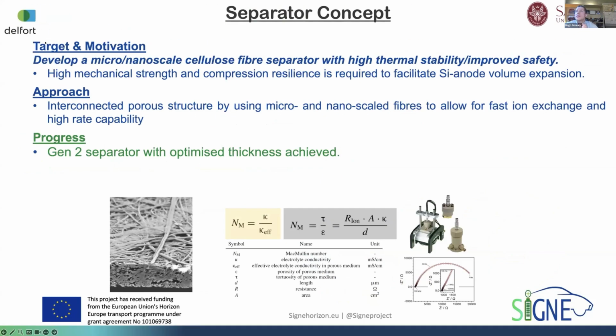On the separator side of things, so these are cellulose-derived fiber separators being developed by Delfort, and they have developed really high-performance non-polymer-based separators. Again, what we found is they're actually beneficial for the anode side of things. When you move to higher silicon content, obviously you'll have material expansion and contraction during cycling, and these paper-based separators seem to be able to buffer some of that volume expansion that we see there. In terms of the electrolyte compatibility as well, these have really good electrolyte uptake values from what we have seen too.